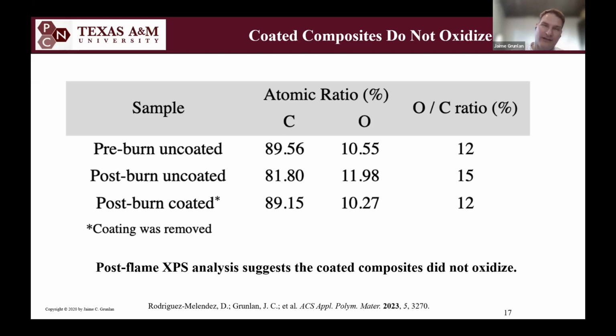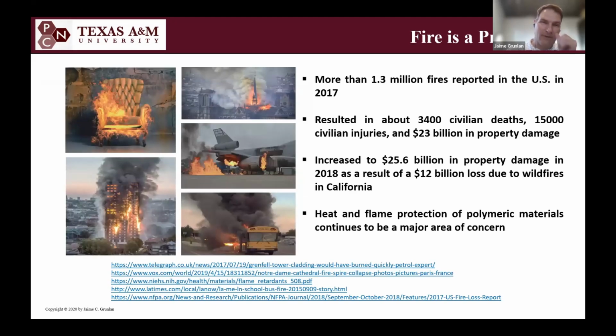With this XPS technique, X-ray photoelectron spectroscopy, I can get the oxygen to carbon ratio, and so that shows me how much oxidation is happening. And once again, if it's an uncoated composite, after that torch is touching it, there's a dramatic increase in the O/C ratios because there's thermal oxidative degradation happening, but we don't see any evidence of that in the coated composite sample. So it's evidence of protecting that composite from the heat of the flame. But that's heat shielding, not flame retardancy.